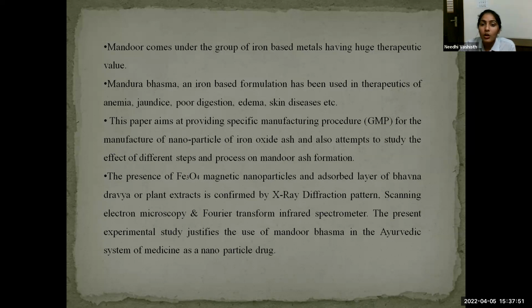This paper aims at providing a specific manufacturing procedure, GMP, that is good manufacturing practices, for the manufacture of nanoparticles of iron oxide ash, and also attempts to study the effect of different steps and processes on Mandoor ash formation. The presence of Fe3O4, that is ferric oxide magnetic nanoparticles, and an adsorbed layer of plant extract is confirmed by the X-ray diffraction pattern, scanning electron microscopy, and Fourier transform infrared spectra, that is FTIR. The present experimental study justifies the use of Mandoor Bhasma in the Ayurvedic system of medicine as a nanoparticle drug.